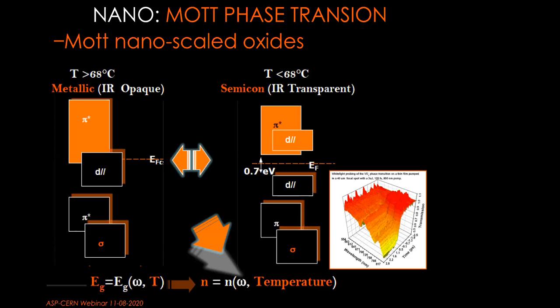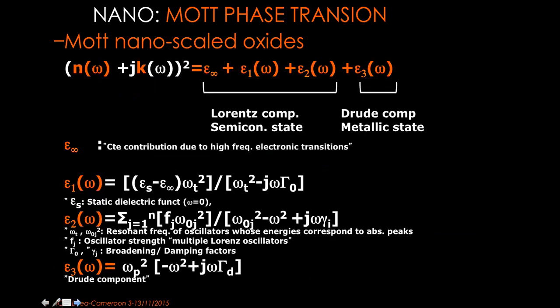So I would like just to stress on the fact that this change from infrared transmissive to infrared opaque is due to the opening or closing of the band gap. It's the orbitals which split and allow that band gap to open or to close. Either there is no band gap in the case of metallic, or there is a small band gap of 0.7. And you will see that the optical properties of this material, due to this opening and closing of the band gap, are extremely important. I don't want to go through the theory.